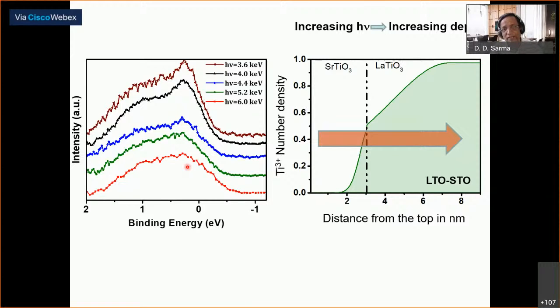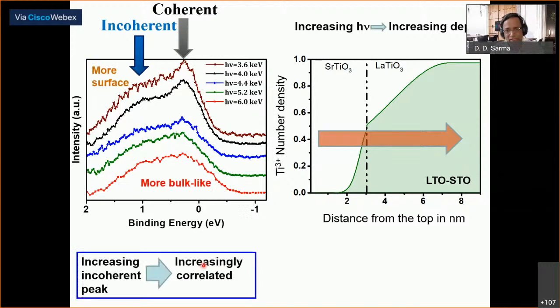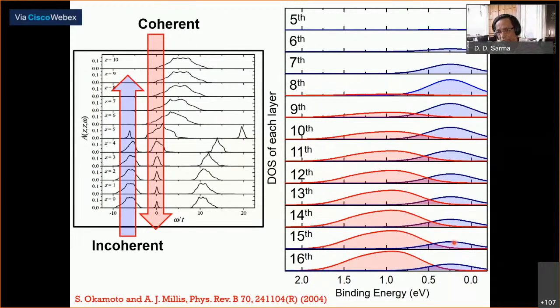But I can in fact extract out exactly how the coherent peak and the incoherent peak intensities are changing. And that is what I'm going to show you next. Beyond this qualitative statement that as I look deeper inside, I see it increasingly correlated, here I've extracted for you from the experiment the coherent intensity in blue and the Mott-Hubbard sideband, the incoherent intensity, in red, layer resolved. You can see this is the Okamoto and Millis paper. It replicates this rather well, except for the fact that the distribution is even more gentle compared to what we see here. Here you see, as I go from the LTO side towards the interface, the Mott-Hubbard intensity is decreasing.